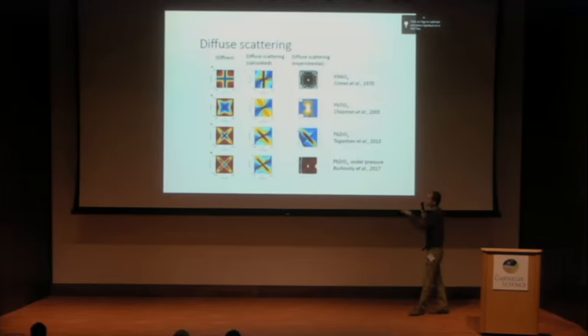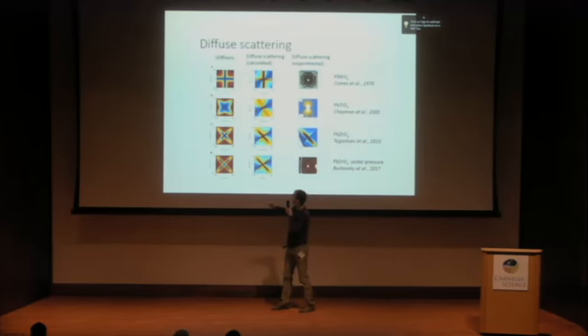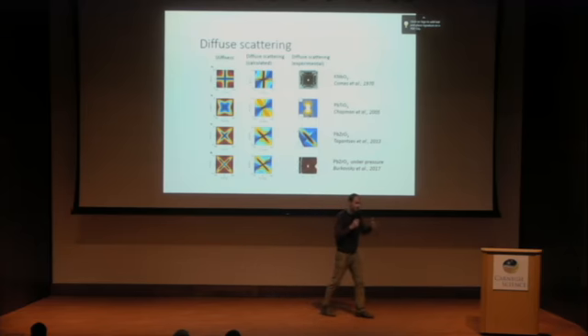And under pressure, we did also measurements of diffuse scattering, and we have registered these maxima of diffuse scattering intensity, and they are easily reproduced by the model by not very large variation of polarizability anisotropy parameters.